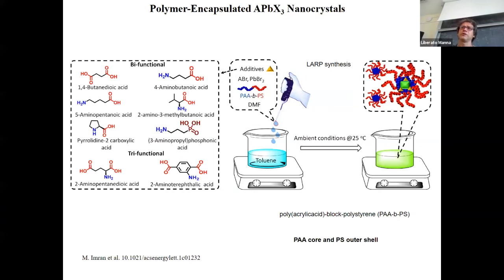Now, another more interesting approach, which was just published by us, is nanocrystals encased in micelles made of polyacrylic acid and block polystyrene. Okay, this synthesis is done by the ligand assisted reprecipitation approach. And together with the polymer and the precursors for the nanocrystals, we also add a set of additive molecules which improve the compatibility between the polymer and the nanocrystal. Now, this block polymer is such that the core is polyacrylic acid, and the outer shell is polystyrene.